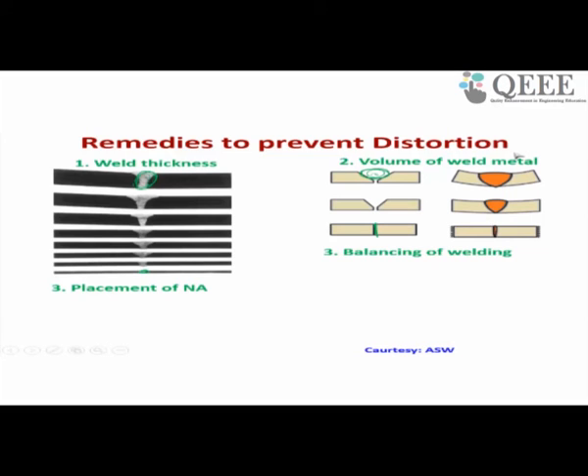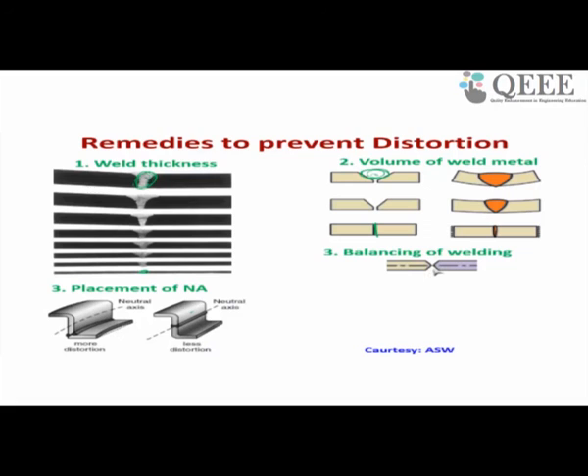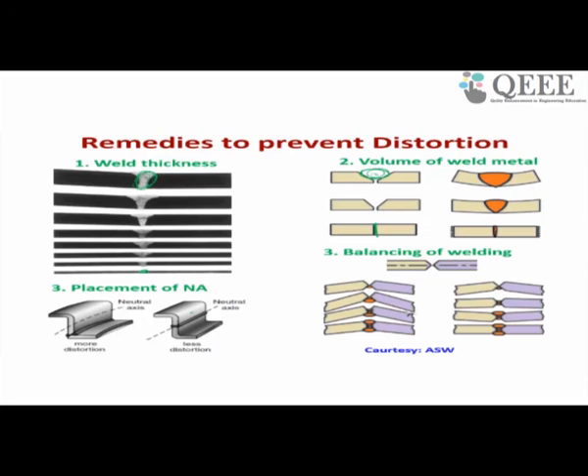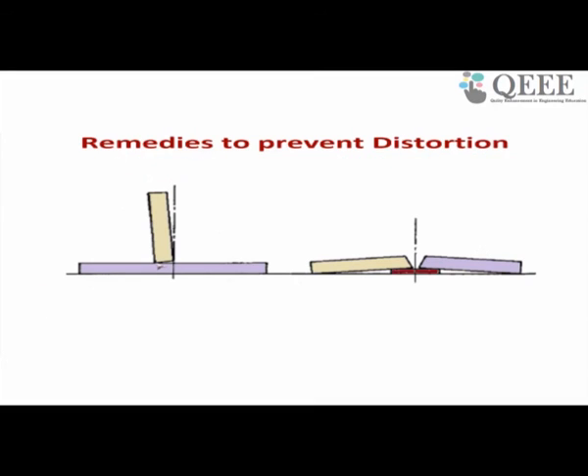So volume of weld metal also plays a major role in distortion. Similarly, if you place your neutral axis like this, then you will have more distortion. If you have the neutral axis at the center, and your weldment happens at the neutral axis, then you will have less distortion. Similarly, you can also balance. Suppose you want to join two pieces like this, then what can you do? If you weld one side initially, then start the second side, you will get high distortion. Okay, instead of doing this, do one side like this, then join the second side, then again join the first side, like that, then you can balance the welding. Similarly, if you know that distortion will happen like this, then you can place your samples beforehand like this, then you can overcome the distortion through the position of welding.